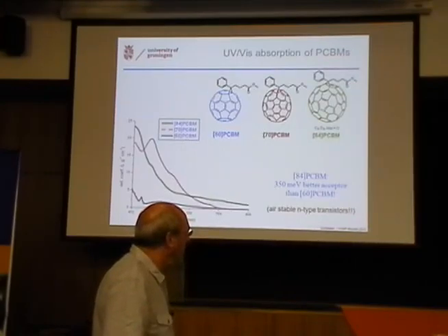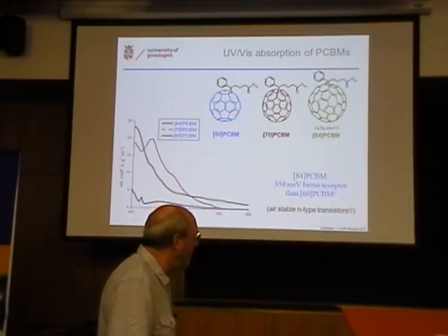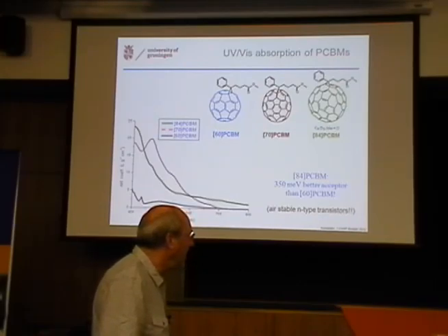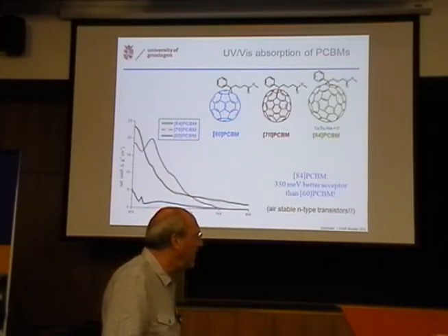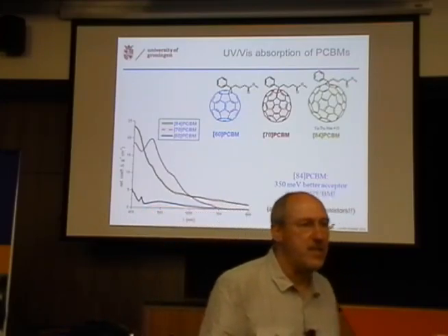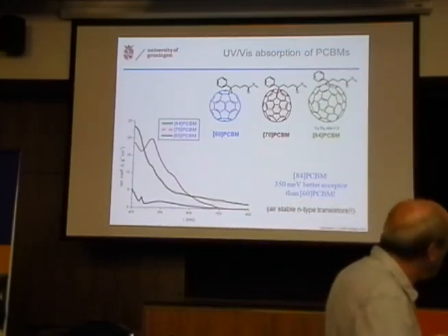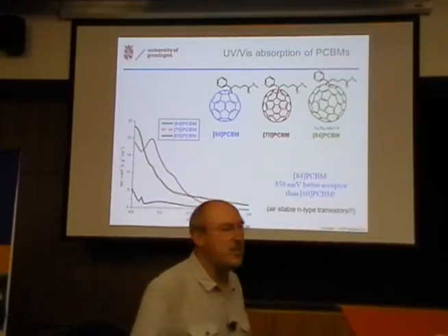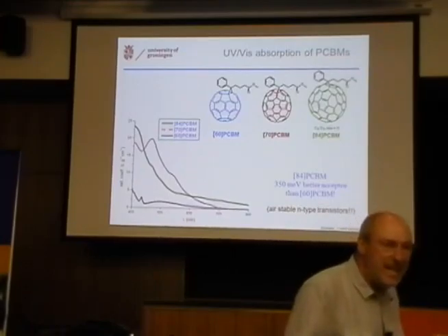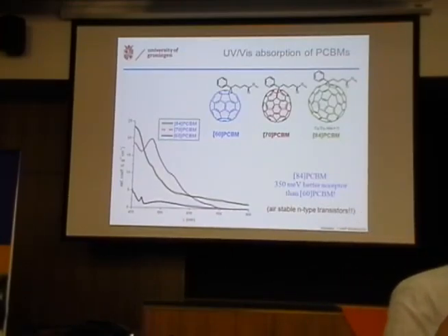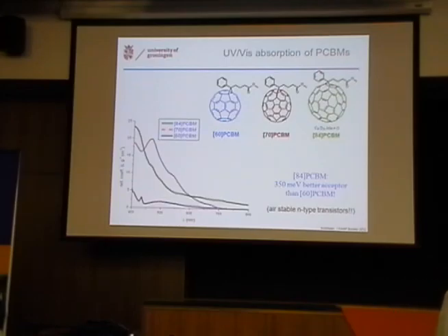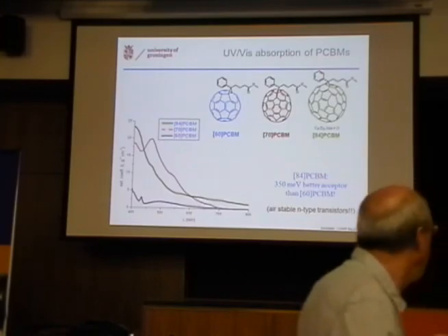So here are the absorption spectra. As you can see, on this scale the absorption of 60 PCBM is really a lot less than that of 70 PCBM in the red line. But you also see that they both end exactly at the same position. The optical band gap for these two materials is identical, which is kind of interesting. I'm not going into that, but it has great advantages because you can use a mixture of these two with many polymers. And that makes the cost situation of organic solar cells a lot more interesting.